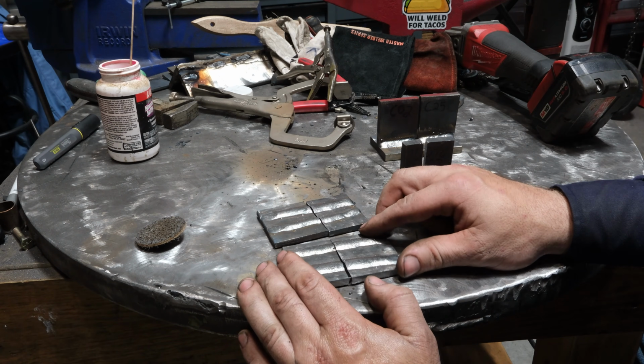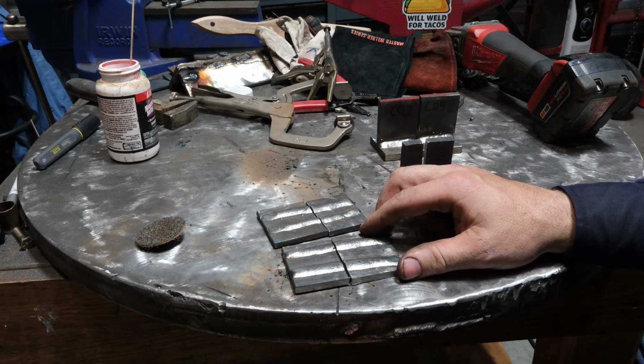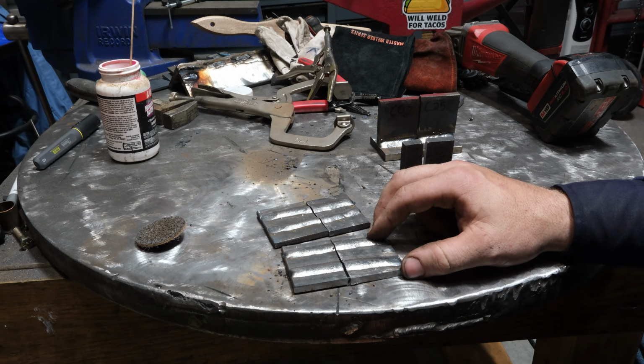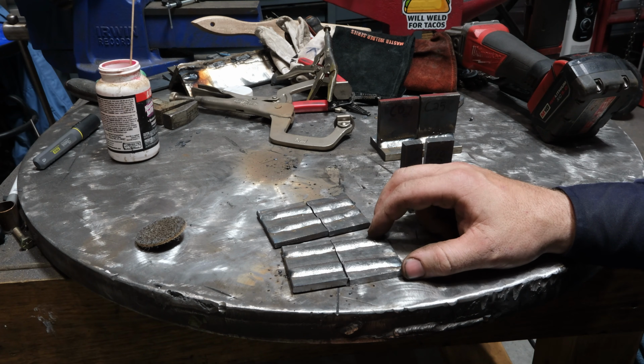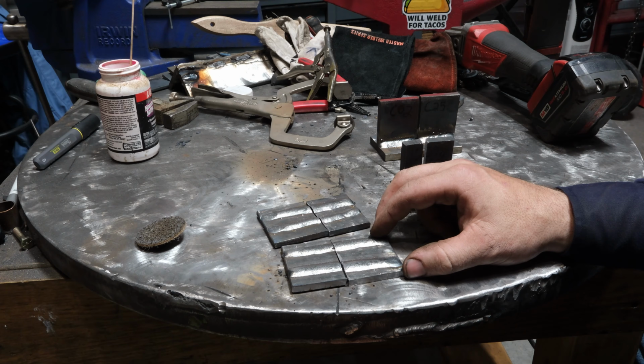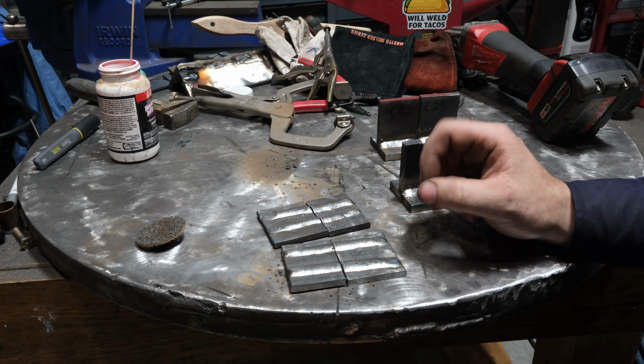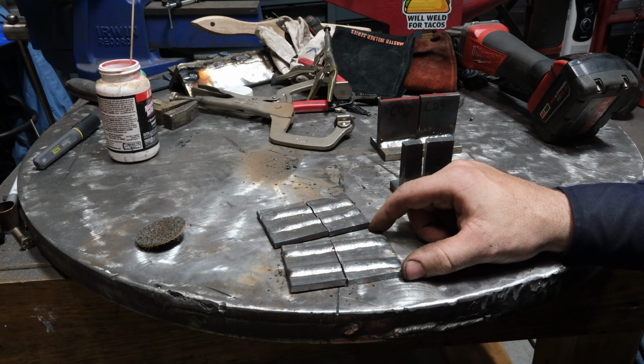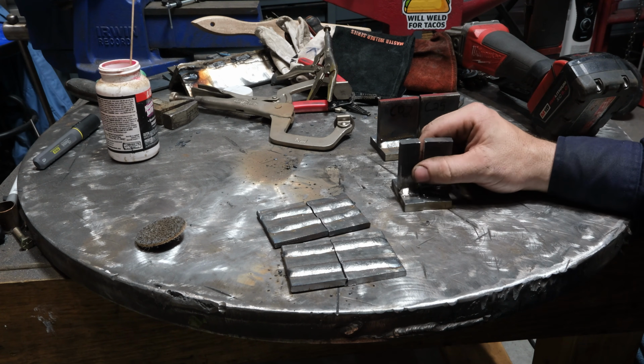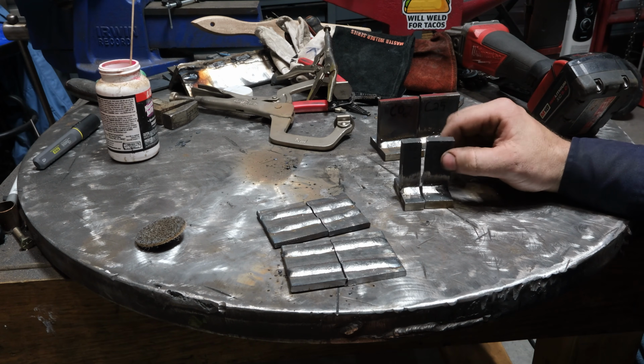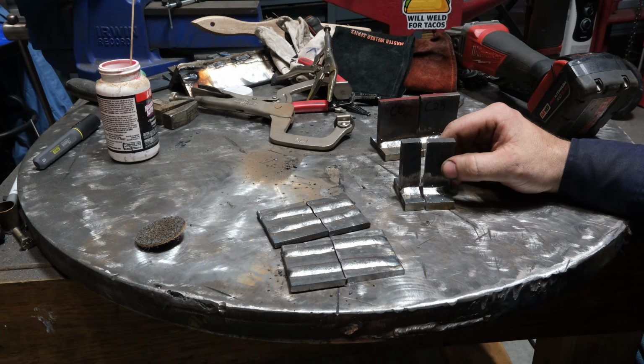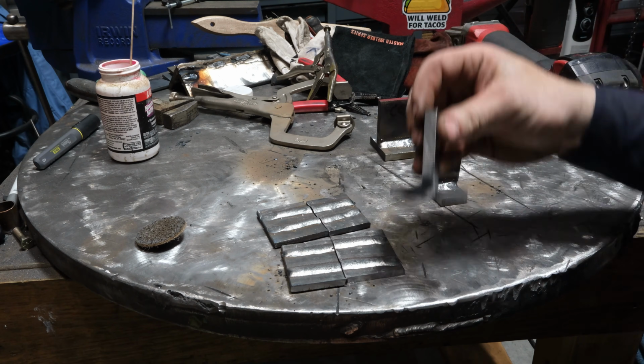So these welds really didn't have that great a penetration, and I'm starting to see a trend here that I don't know that this stuff is really going to have that great a penetration. It more or less seems to be like a 7018 where it has really good sidewalls, so the width of it is good on the penetration end, but the actual depth of it is somewhat limited, and that's kind of why I did this extra where I used the same settings as on this plate and ran a fillet weld with 100% CO2 gas just to see where we're at. So let's take a look at that.